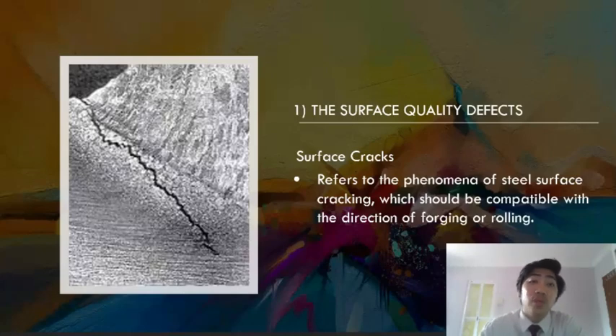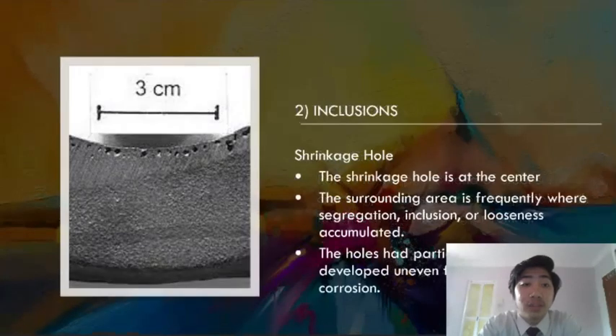So the second defect is inclusion. Example of the defects is shrinkage hole. In the specimen with low magnification, the shrinkage hole is located in the center, and the surrounding is often the place where segregation, inclusion, and looseness aggregate. Sometimes the cave or gap can be seen before corrosion. After the corrosion, the hole partially darkens and shows irregular folds.